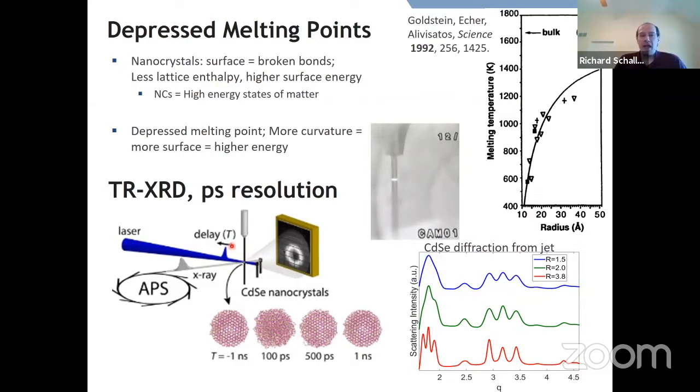And then we average what the signals look like there for a long time at one delay, then we change the delay, make more measurements and so forth, and can build up something that looks like transient absorption, but it's X-ray diffraction as a function of pump probe time delay. And we can change the pump fluence, and we can change the nanoparticle sample and so forth. Okay,